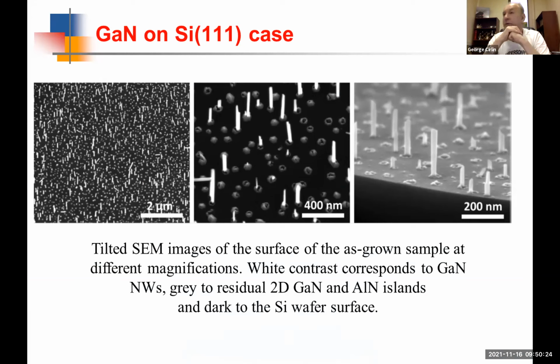I remember it was something like 5 years ago when we started completely different work. We would like to investigate the piezo properties of the nanowires, and in this case, we got a sample from Jean-Christophe Stock, having gallium nitride nanowires grown on silicon with quite small density, and also aluminum nitride islands were used to proceed the growth of gallium nitride nanowires afterwards.